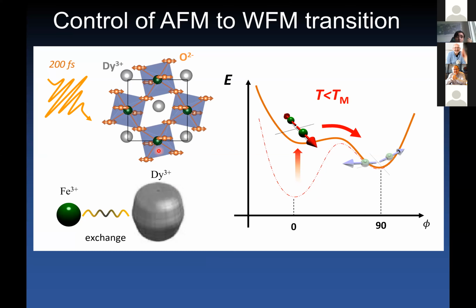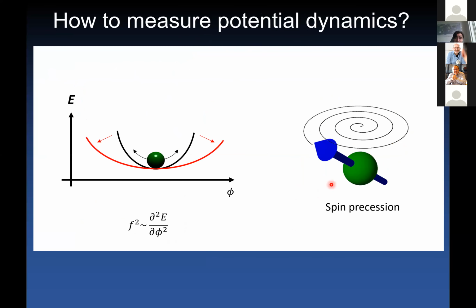So, control of switching from an antiferromagnetic phase to a ferromagnetic phase via manipulation of the crystal lattice. The key aspect here is to be able to measure the shape of the magnetic potential. This is typically done by exciting spin precession. If you excite spin precession, you will measure some frequency of oscillations of your magnets, and this will reflect the local curvature of your magnetic potential.